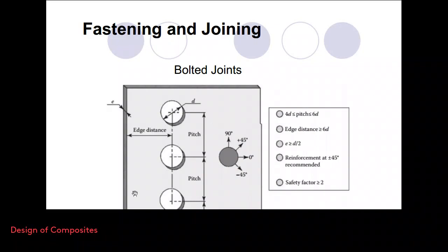Generally, the stress around the hole is not in one direction. Even though you apply a tensile load, you have a complex state of stress around the hole. As a result, you need fibers which are oriented off-axis, so it can be positive 45, negative 45, or in some other directions, and mainly the safety factor or design factor shall be bigger than 2.